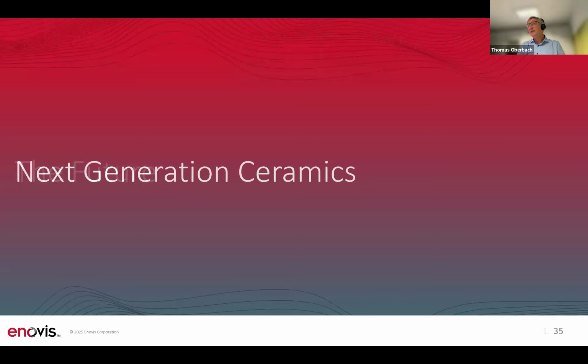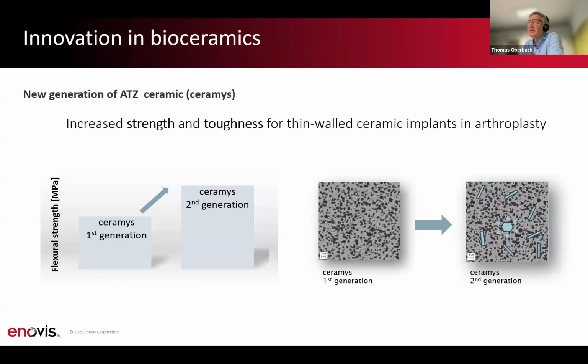What we will do in the future. One point, and we are working on this point, is to create a new generation of ATZ ceramic. We call it ceramys second generation, and the target is to increase the strength and the toughness again for the realization of very thin wall ceramic implants in arthroplasty. Because when we can decrease the wall thickness of the implant, then the surgeon has the possibility to preserve more bone stock, and so this is one target, and we have some projects at the moment where we investigate this, where we develop this new ceramic, this ceramys second generation. We want to use also the in situ formation of platelets to increase the toughness and the strength again.